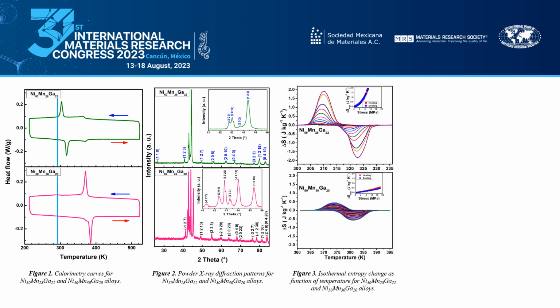Figure 3 shows the isothermal entropy change for the two alloys. The maximum values of isothermal entropy change obtained for the 5M alloy were 1.91 and 1.83 joules per kilogram Kelvin during cooling and heating when applying 10 megapascal. For the 7M alloy, the maximum values were 0.19 and 0.26 joule per kilogram Kelvin during cooling and heating when applying 10 megapascal.